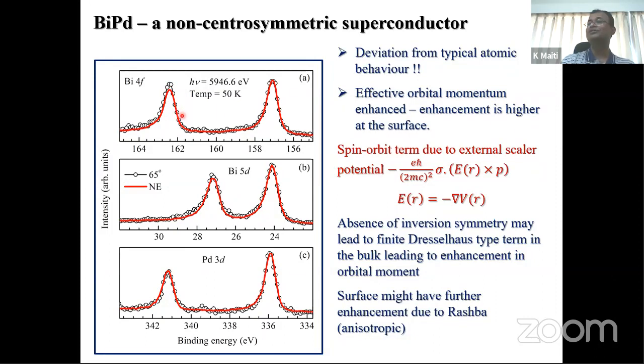So this is something unusual because normally you know that in this effective quantum picture, the branching ratio, which means the intensity ratio between these two peaks, should be 2j plus 1, where j is the total angular momentum, which is L plus S or L minus S. But here we see that that is not followed.